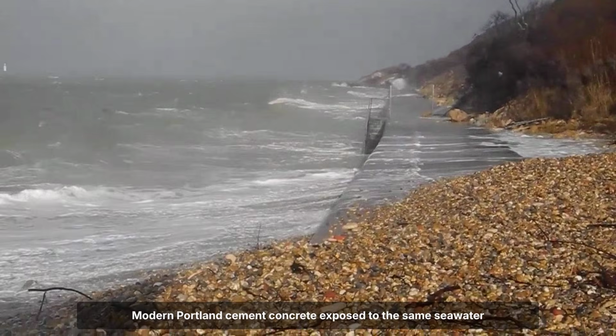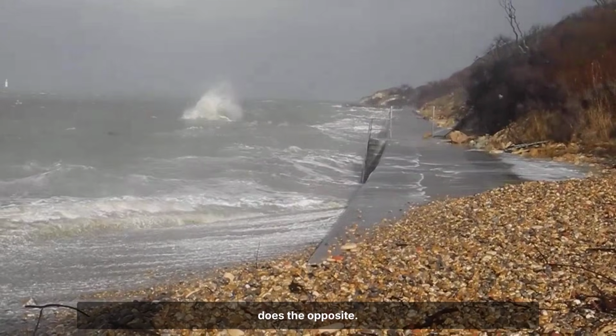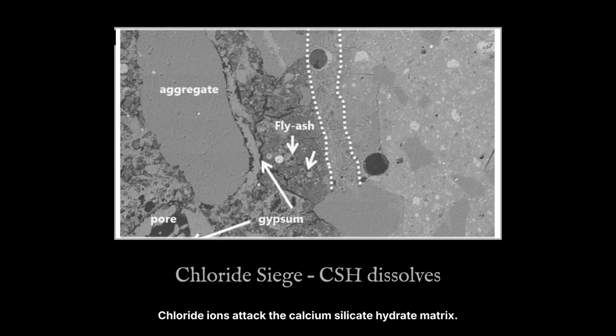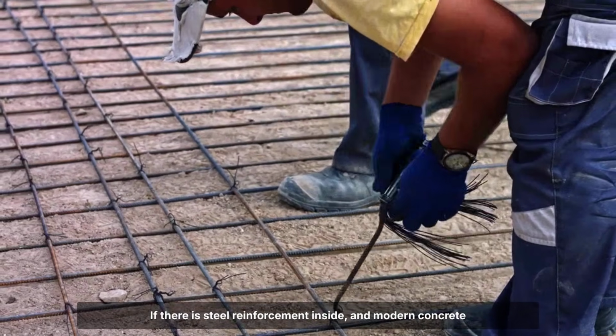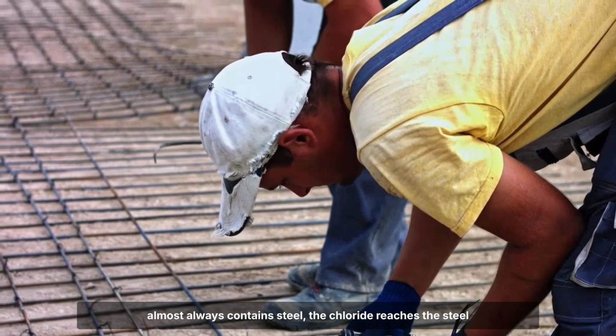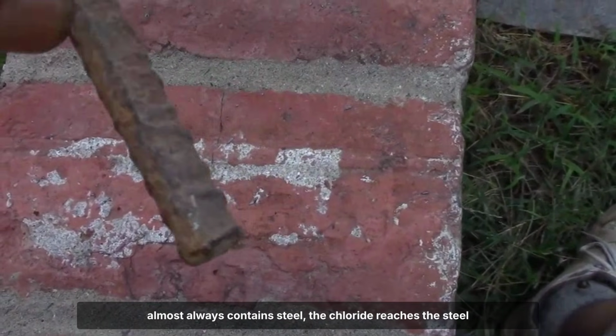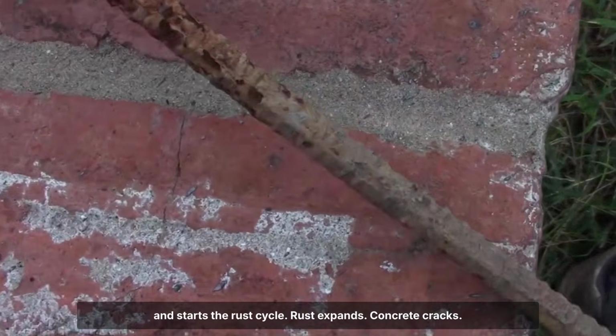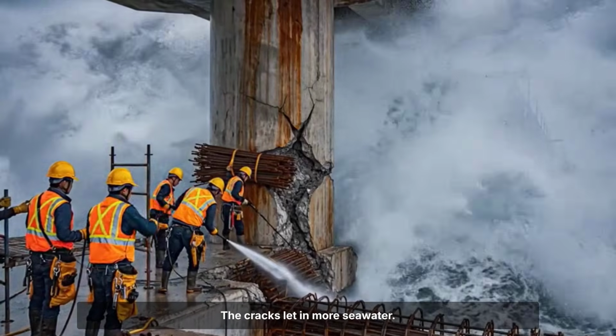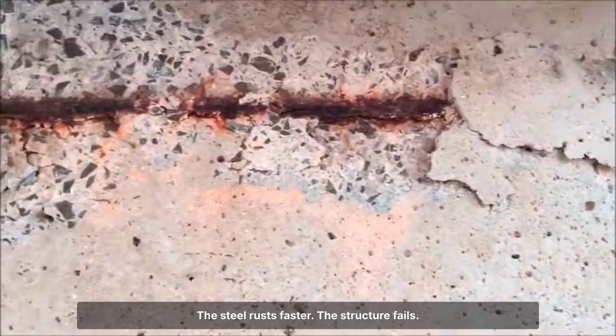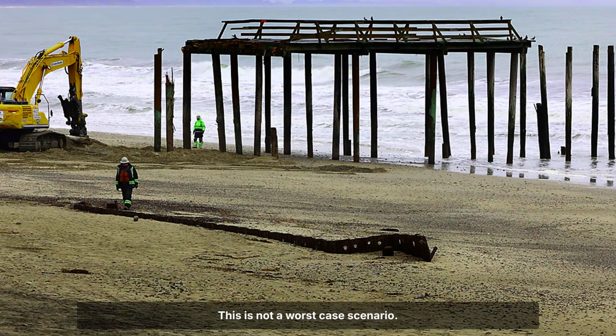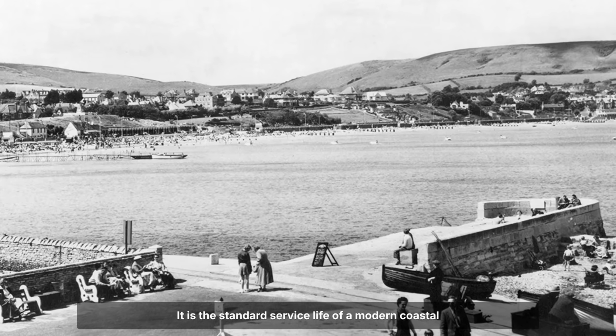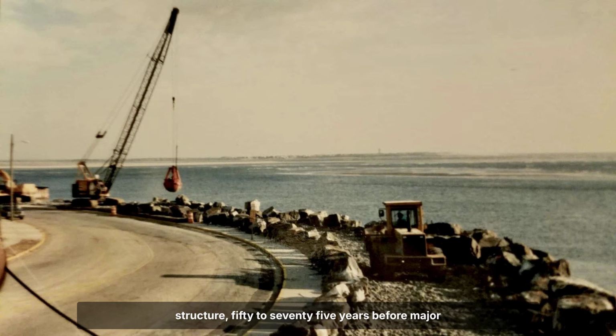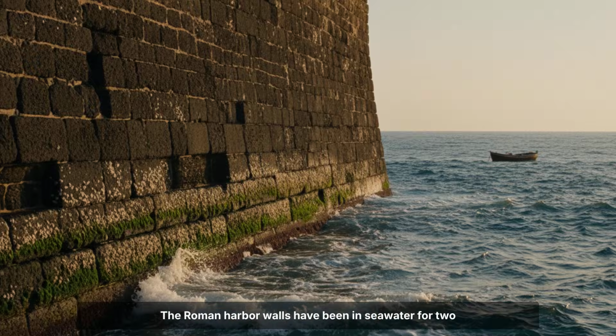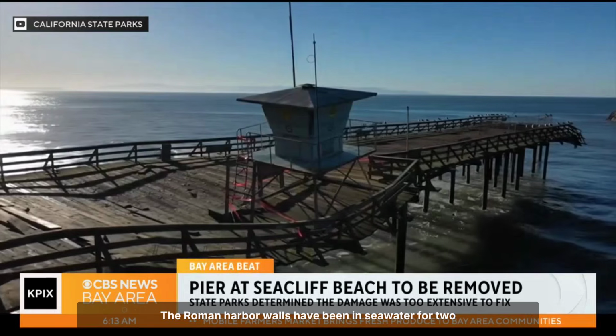Modern Portland cement concrete exposed to the same seawater does the opposite. Chloride ions attack the calcium silicate hydrate matrix. The concrete softens. If there is steel reinforcement inside, and modern concrete almost always contains steel, the chloride reaches the steel and starts the rust cycle. Rust expands, concrete cracks, the cracks let in more seawater, the steel rusts faster, the structure fails. This is not a worst-case scenario. It is the standard service life of a modern coastal structure, 50 to 75 years before major rehabilitation is required. The Roman harbour walls have been in seawater for 2,000 years.